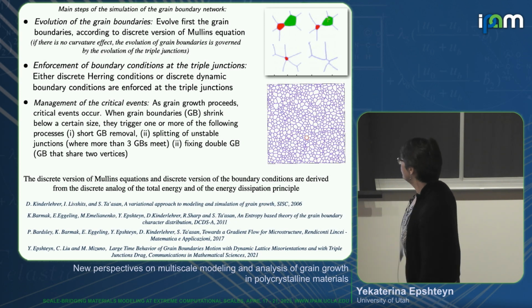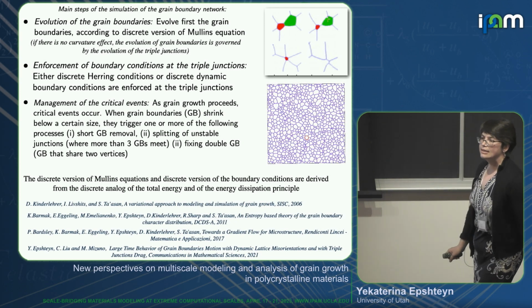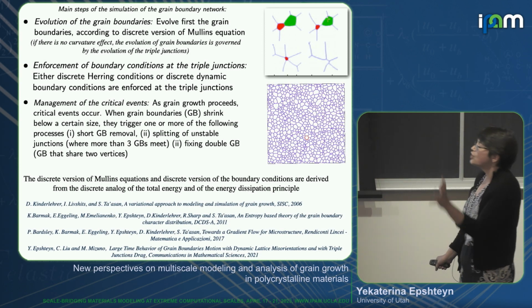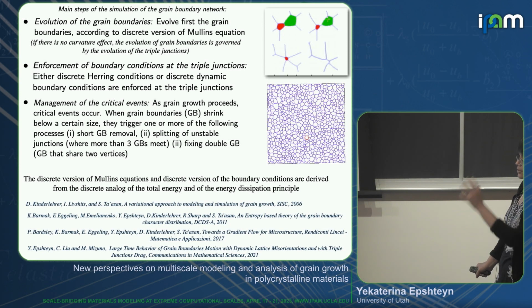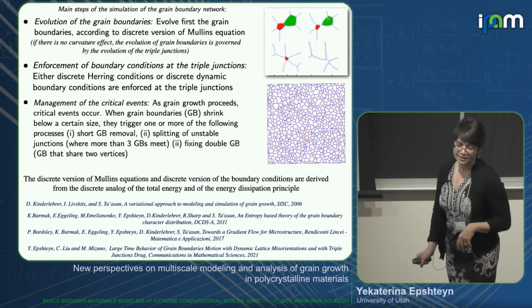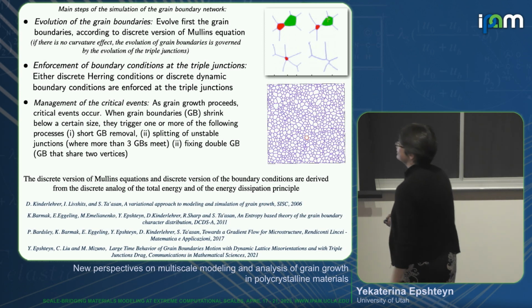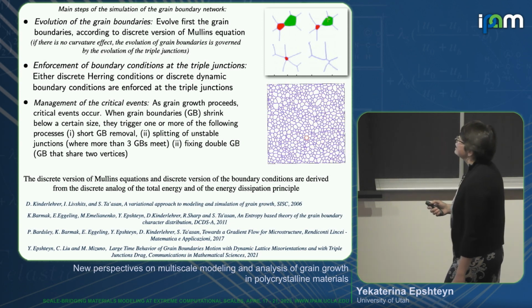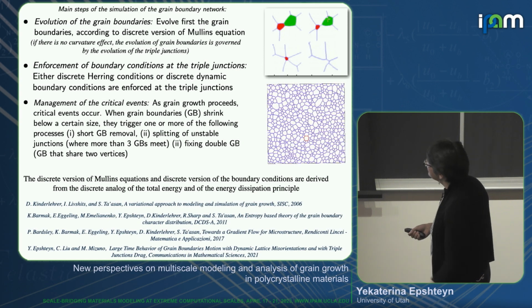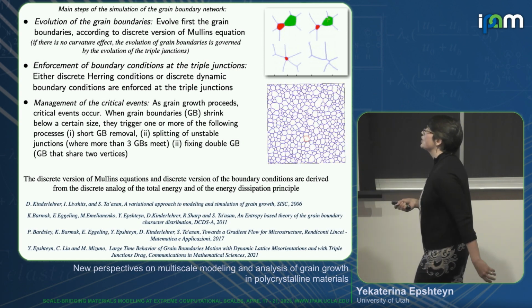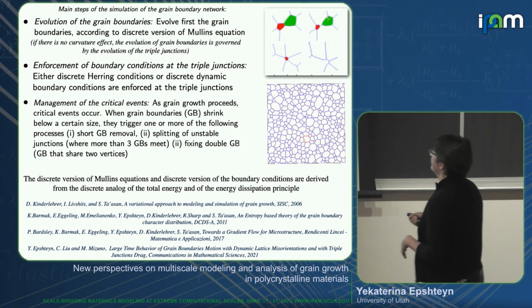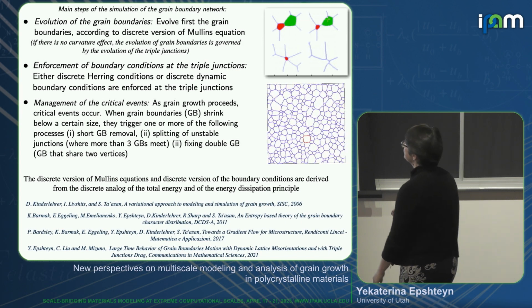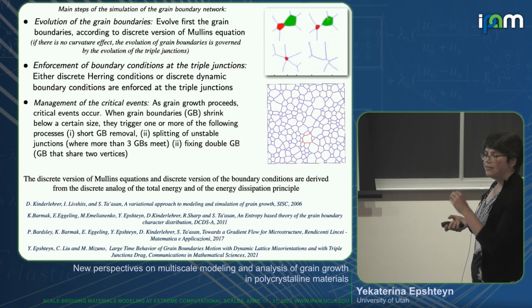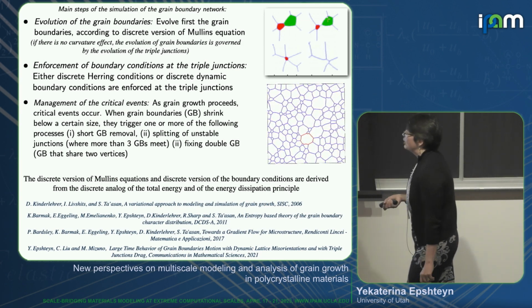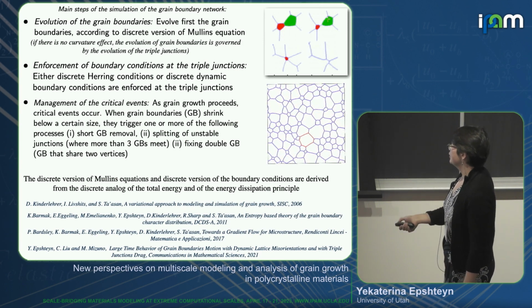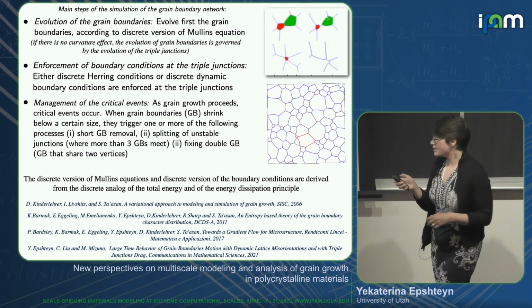And I guess the most challenging part in the sharp interface approach is handling of topological events, because it's not just for numerical simulations; for mathematical analysis, it's also a major challenge to analyze this system and take into account topological critical events. It's not just that grains disappear, but short grain boundaries are being removed via splitting of unstable junctions, and sometimes via the appearance of double grain boundaries. So everything has to be handled in a way that enforces, in our model, we assume maximum dissipation. More details about numerical simulations can be found in one of these papers.